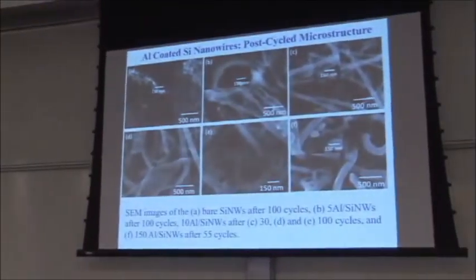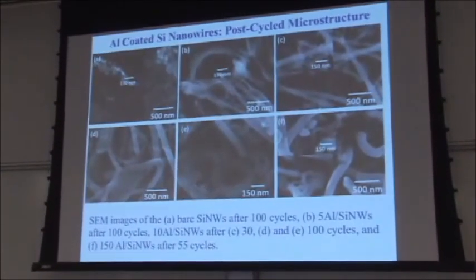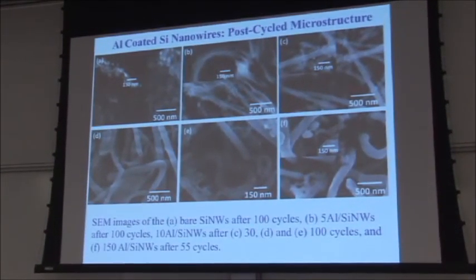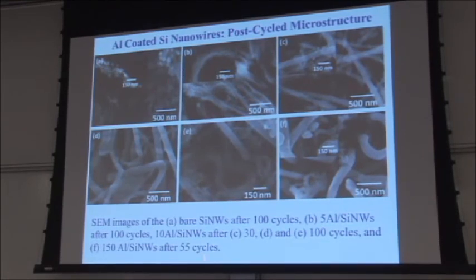And if you look at the nanowires, this is kind of a classic, I wouldn't even call it a failure mode, but a classic cycling microstructural evolution of nanowires. So you start out with wires, and during cycling, they almost split. Like you take a pair of scissors and just chop them in half and half and half lengthwise, so they kind of shred. And the post-cycle microstructure, this is after 100 cycles, for the bare silicon nanowires looks like this. So it's kind of this, again, separated, very high SEI layer mess. If you have a thin coating, they seem to be more intact. If you have a thicker coating, so if you have a 10 nanometer coating, they seem to be quite intact.